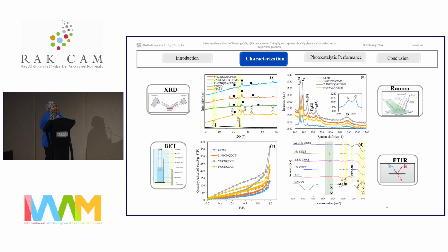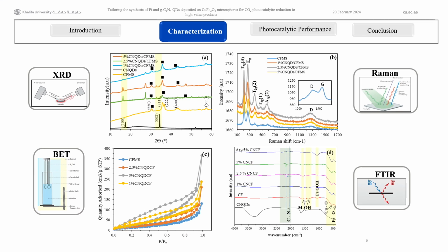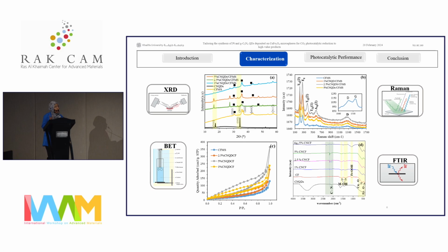So the system that we proposed is copper ferrite with graphitic carbon nitride quantum dots and silver nanoparticles. We did different characterizations for the nanocomposites, starting with the XRD. We observed the diffraction planes assigned to cubic copper ferrite, and the diffraction phase related to graphitic carbon nitride with a slight shift in the 002 peak, which was due to the lattice compression.